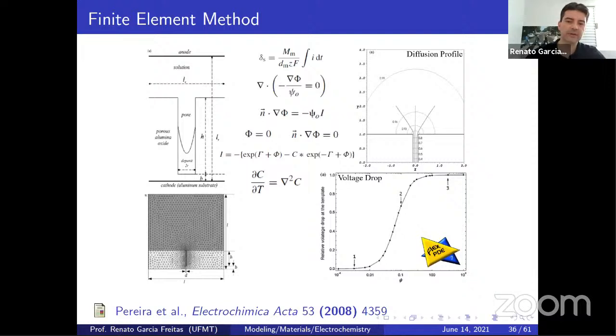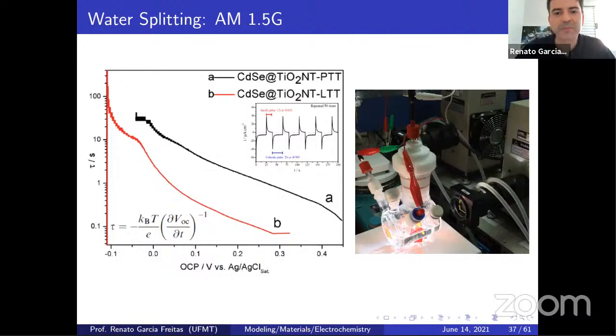So how to solve this problem? Use a very easy approach, the second Fick's law. Why? If you have two systems, the previous thermal treatment and the later thermal treatment, and we applied anodic pulse and cathodic pulse, anodic pulse, cathodic pulse. As soon as we apply the anodic pulse, we deposit selenide, and we apply the cathodic one to deposit cadmium. Alternating, cadmium gets inside, selenide gets inside, with short pulses so we don't block the surface, and we deposit over the whole nanotube. We use the Professor Juan Bisquert approach to study the open circuit voltage decay.